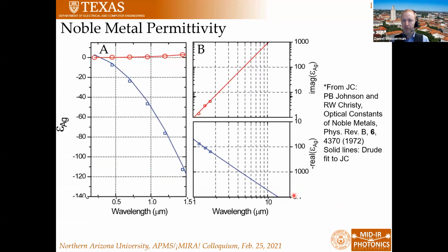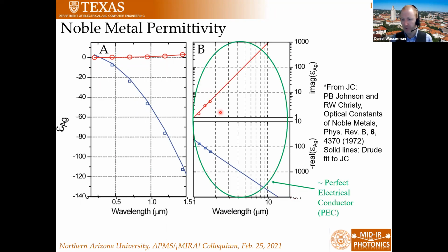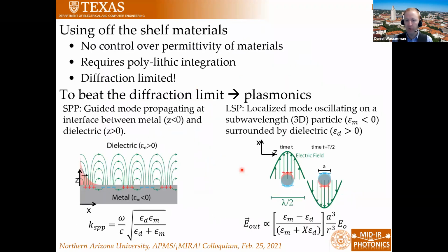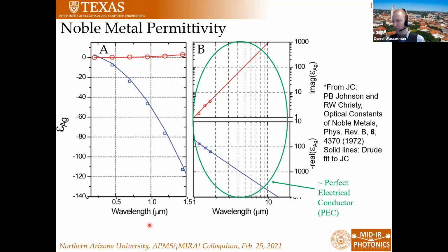And if we look first at the permittivity of a typical noble metal, one of the things that we notice is that in the mid-infrared, our metal is essentially a perfect electrical conductor. So the permittivity is remarkably large and negative. So it behaves like a perfect electrical conductor. It's highly reflective. And if we look at the expression for our surface plasmon polariton wave vector, we see that in this regime, basically what you have is a guided mode that has the wavelength of light in free space. So it's guided in the sense that it is a surface mode, but it's not tightly bound to that surface, because the permittivity is so large and negative.